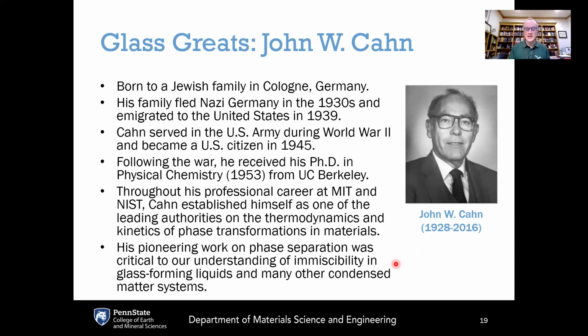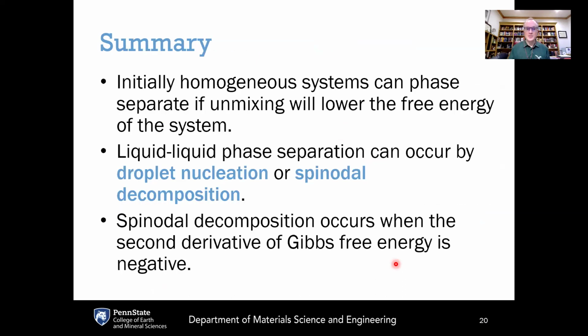So to summarize, initially homogeneous liquids can phase separate if that unmixing will lower the free energy of the system. Liquid-liquid phase separation can occur by droplet nucleation or spinodal decomposition, and that depends on the sign of the second derivative of the Gibbs free energy.